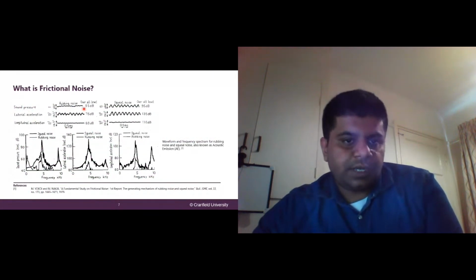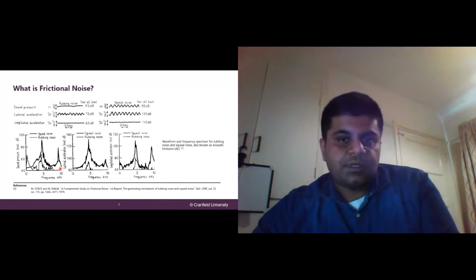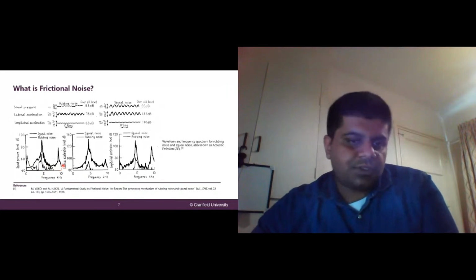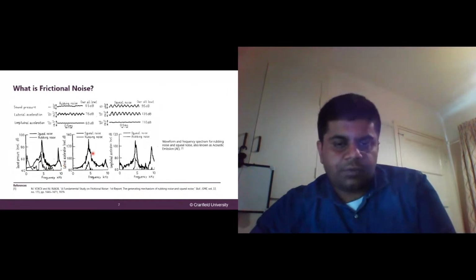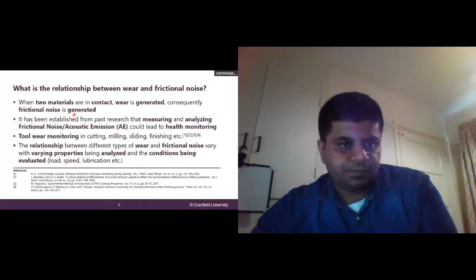So if you look at the amplitude of these two sound pressures, rubbing noise has like 65 decibels of sound pressure, sorry. And the squeal noise goes all the way to 95 decibels and it keeps on increasing. So these transient waves that you see on top of here are actually squeal, and the small, repetitive ones that go underneath are usually rubbing noises. So this is a common trend that you see in any sound signal that is generated while a sliding wear is taking place. So what is the relationship between wear and frictional noise?